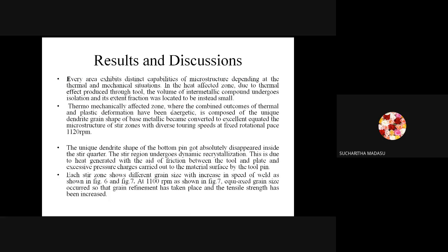And here, the thermomechanically affected zone, where the combined outcomes of thermal and plastic deformation, is energetically composed of the unique dendrite grain shape. Where the temperature distribution is proper, there we can get the dendrite grain size. At that time, the ultimate tensile strength will also be more because of grain size. The unique dendrite shape got absolutely disappeared. Actually, when we start the friction stir welding, the tool pin, whatever we have taken, 6 mm diameter, fully merges with the workpiece. So if more speeds are used, the pin may vanish.